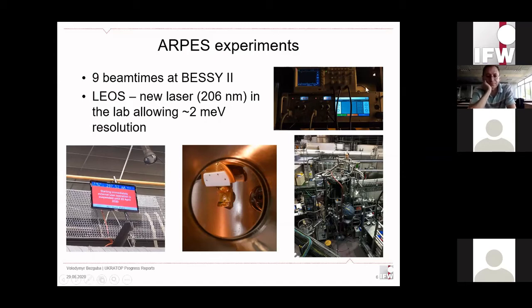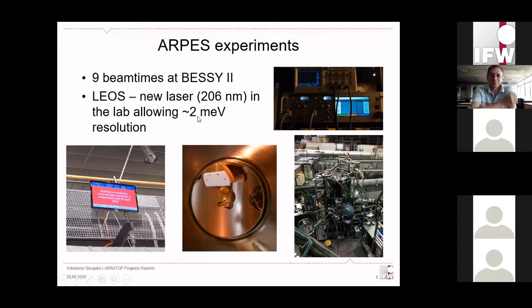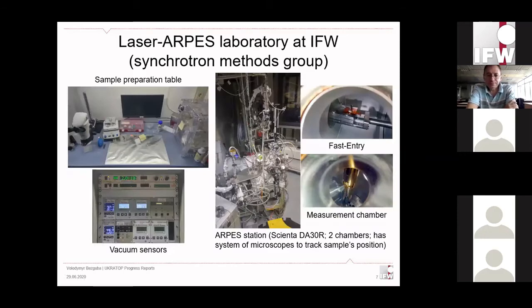Also, in the lab we are currently working on an installation. We set up a new laser and are now working on polarization. The very nice thing about this new laser is that it uses an energy of 6 eV, which is a typical energy for a laser, but we can achieve a resolution as high as 2 meV, which in principle is even better than we have at the 1-cubed beamline at best. So it's better than at a synchrotron.